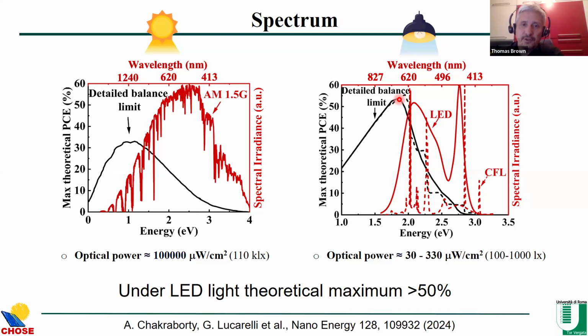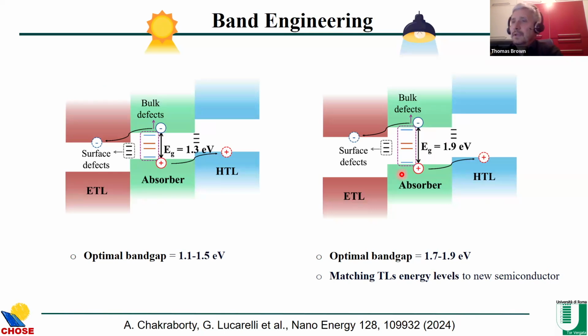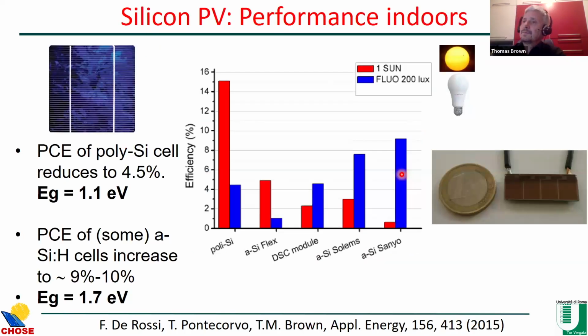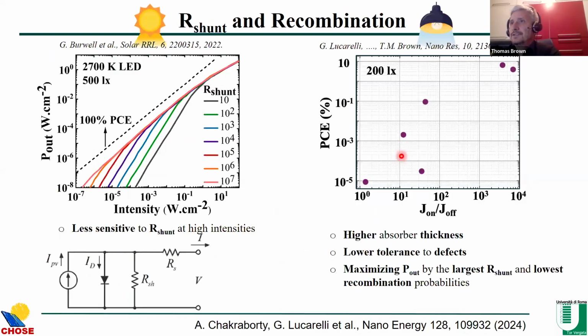And amorphous silicon, when it's hydrogenated, which it is in commercial products, has a band gap of around 1.7 eV. That's one of the main reasons why the efficiency jumps when going from outdoor to indoor illumination. So polycrystalline 1.1, amorphous silicon 1.7, and these jumps. Amorphous silicon also has a high shunt resistance. So the other thing we need to consider, if this is the equivalent circuit, so this is the shunt resistance, which leads to recombination losses. This is the series resistance, which leads to drops in voltages and fill factors.